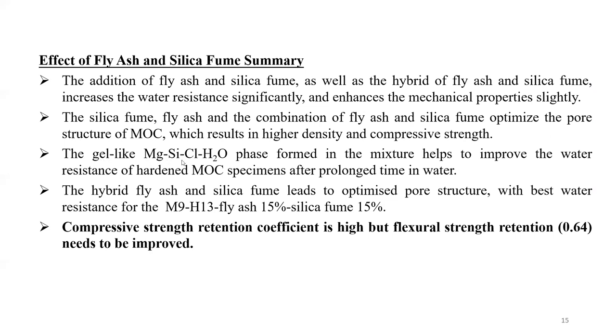The gel-like Mg-Si-Cl-H2O phase formed in the mixture helps to improve the water resistance of the hardened MOC specimens after prolonged time in water. The hybrid fly ash and silica fume leads to an optimized pore structure with the best water resistance for the M9H13 with fly ash 15% and silica fume 15%. The compressive strength retention coefficient is high, but the flexural retention strength is 0.64, still needing to be improved.